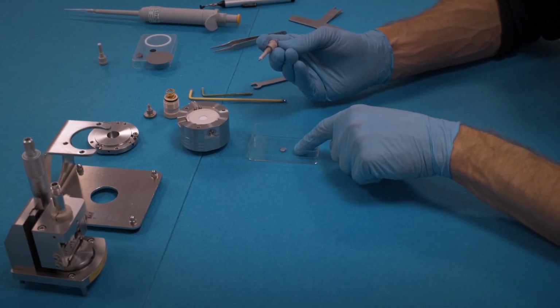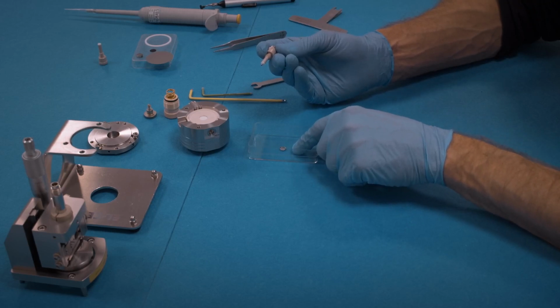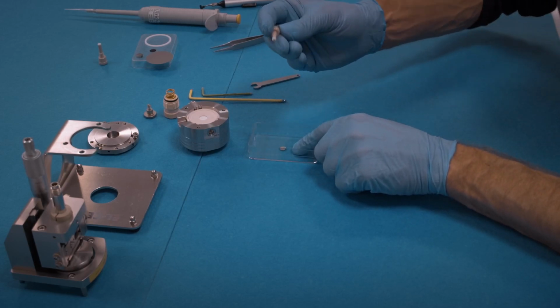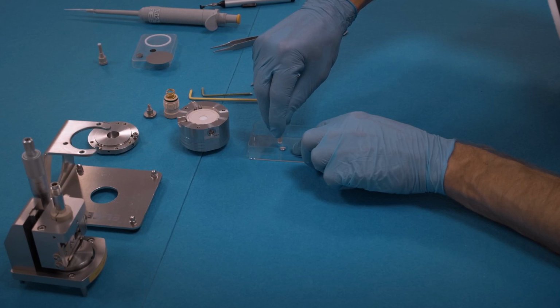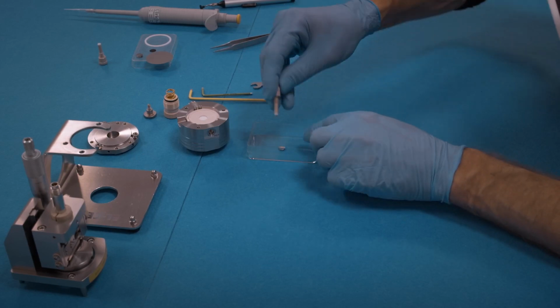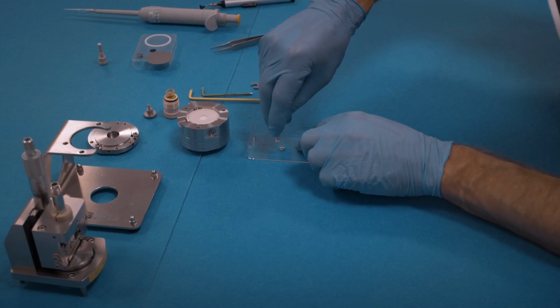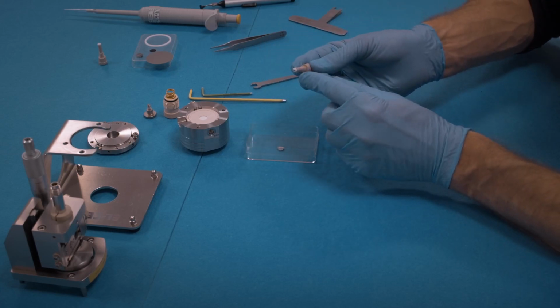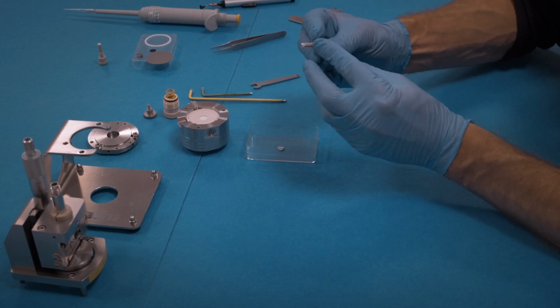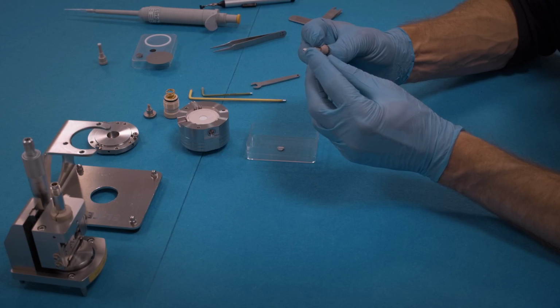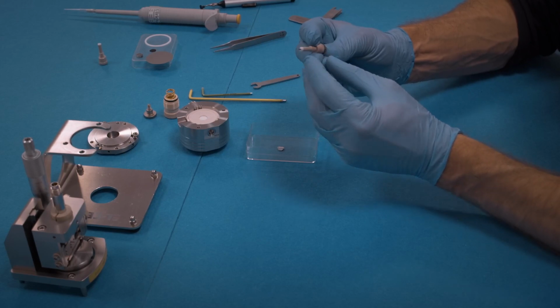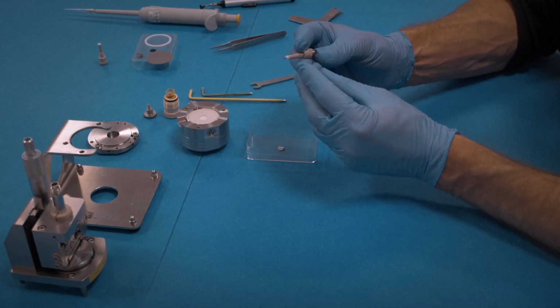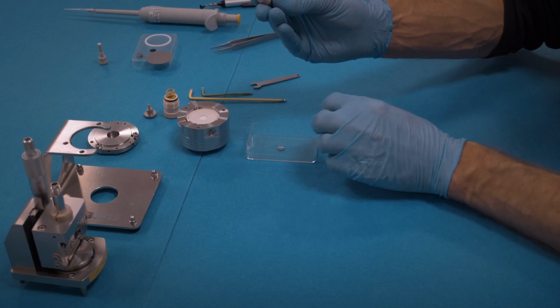And then pick up lithium metal. Put the lithium metal on a polyethylene foil or similar plastic foil. Press the reference pin onto the foil. While doing so, you have to press on the button of the reference assembly to prevent that the PTFE ferrule is getting in contact with lithium metal, which has to be prevented.